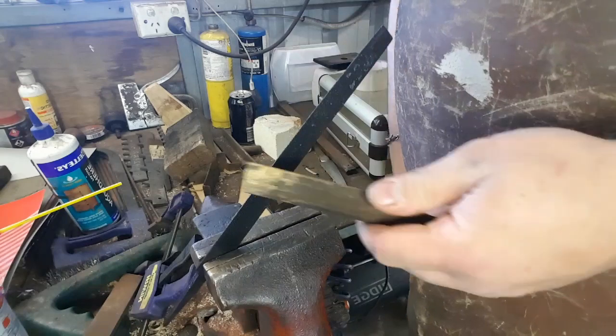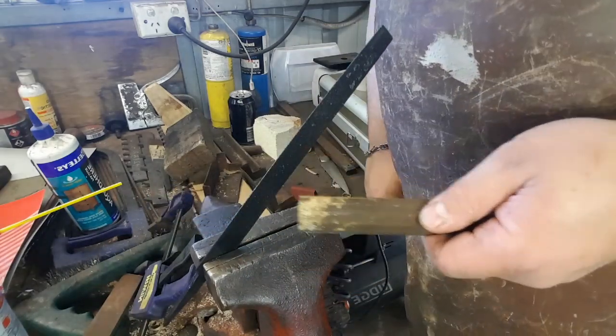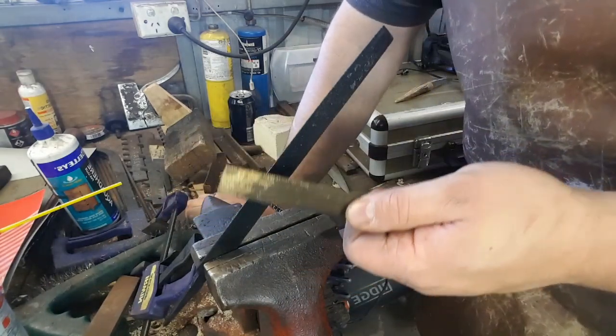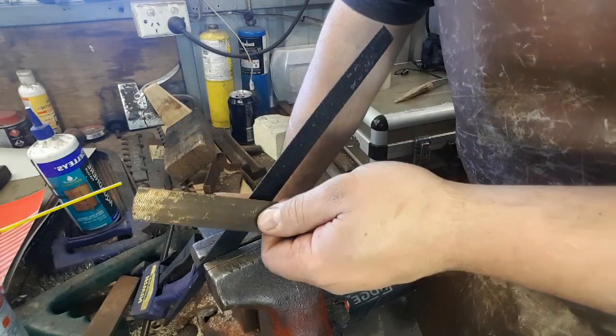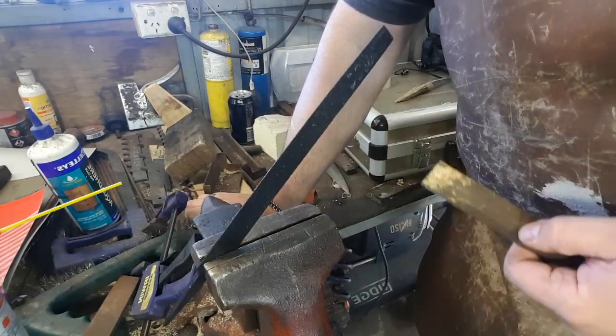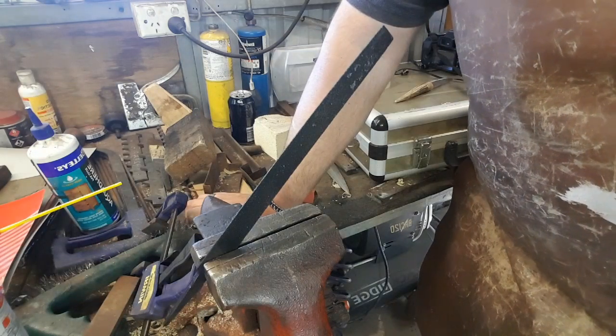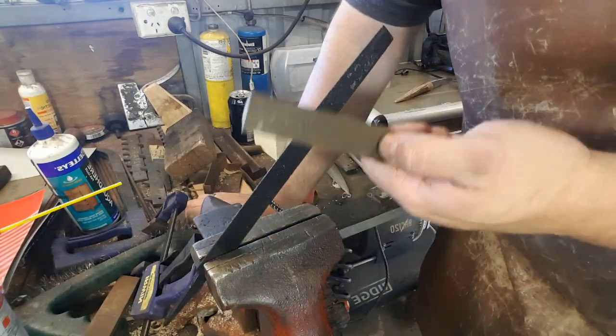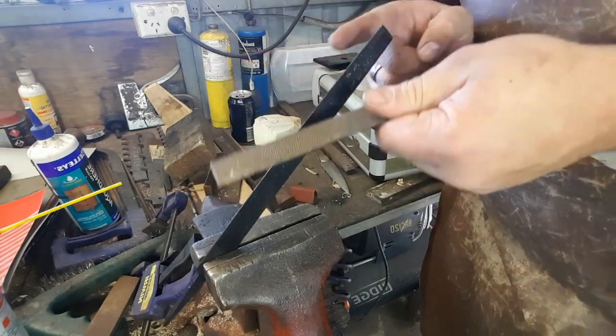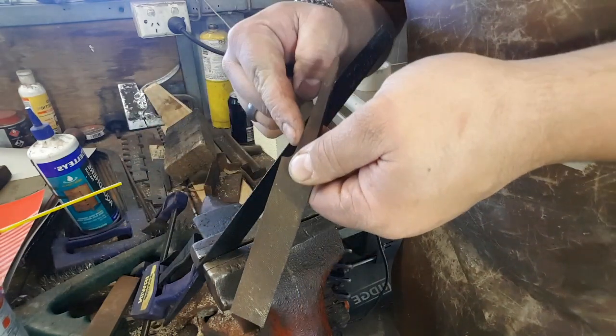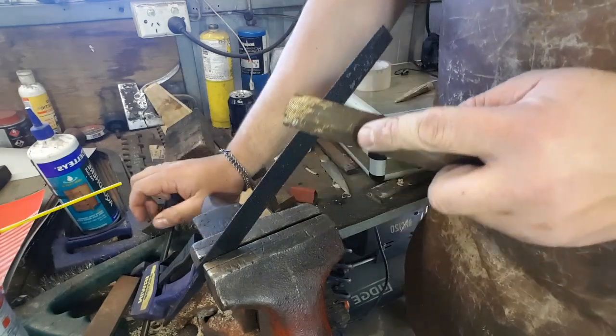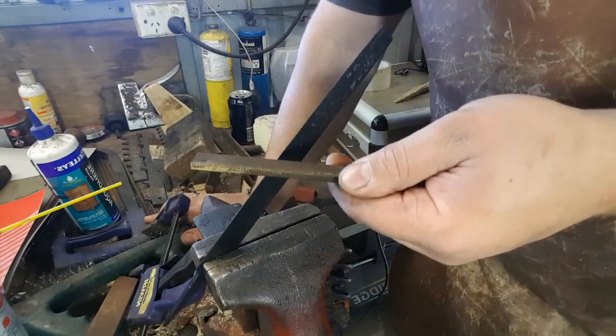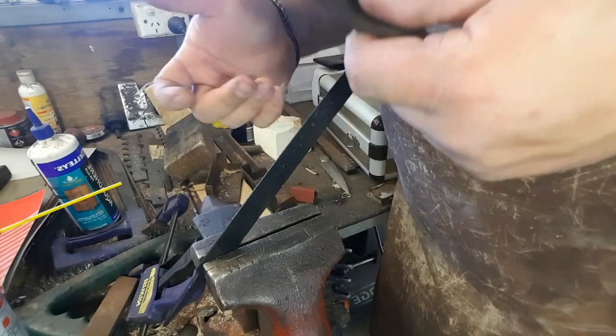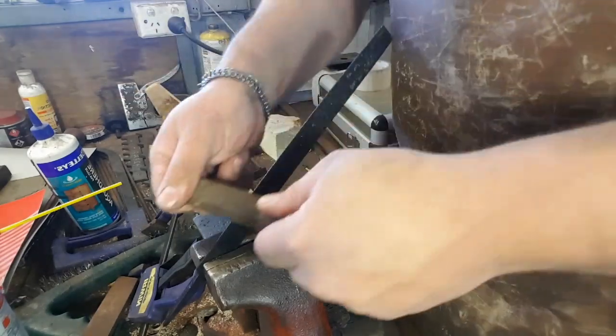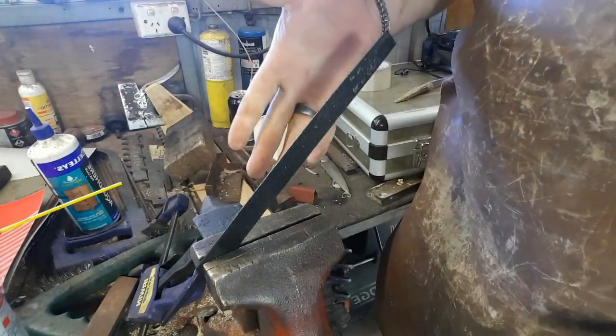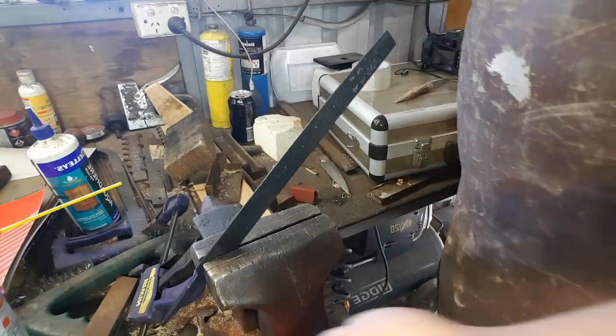Now the important thing is, if you drag your file backwards on the steel, I see a lot of people doing this when they're testing the hardness. They'll drag the file backwards over the edge of a piece of steel to test the hardness. That doesn't tell you anything because files only cut in one direction, and that is away from the tang. So this is the tang of the file. It only cuts in that direction. So you really want to go at it, which is why I use an old file. I don't care if I damage it. I want to know, can I remove material, which in this case, I can't.